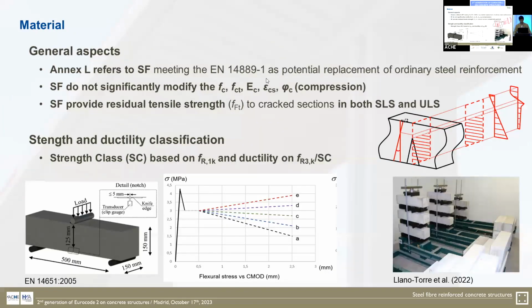In terms of material, the use of steel fiber reinforced concrete, or the steel fibers, initially does not modify significantly the mechanical properties of the material: the compression, tensile pre-crack strength, the modulus, the shrinkage, and the creep in compression. In case the permanent loads are high and the crack width in service is expected to be high, then the creep in tension can be a determining parameter. And in this case, the Annex L proposal suggests making a test to calibrate or characterize the creep behavior in tension.